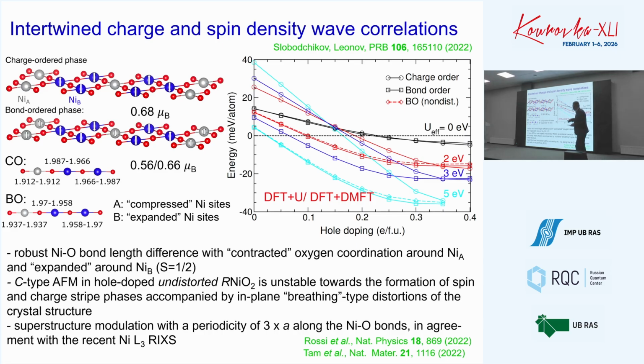On first glance this is very unusual, some kind of combination of spin and charge density wave. But I would say this is typical behavior for nickelates, I mean for doped lanthanum-2 nickel O4 oxides, in which upon doping you can obtain a zoo of many different magnetic, charge-ordered magnetic states. And we reproduce one of those. What is particularly interesting is the formation of ferromagnetic zigzag lines, like in doped charge-ordered manganites. Yes, this is a lot of fun.